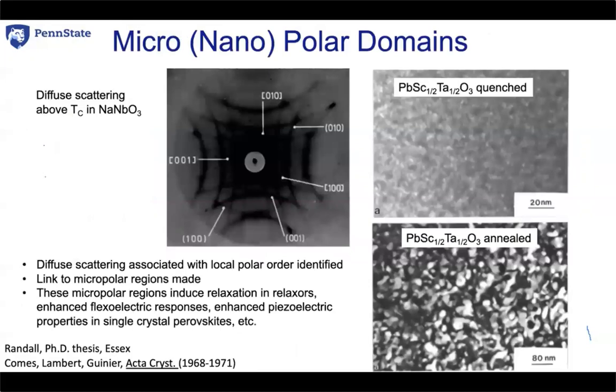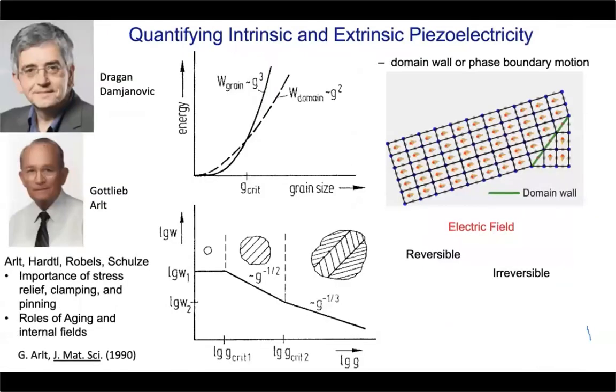Key early work on identifying nanopolar regions came from people like Clive Randall. This is from his PhD thesis at Essex University, where he was able to demonstrate in the TEM the observation of micropolar regions. This really was a confirmation of things that had been proposed by people like Comes, Lambert, and Guinier, that there would be residual polar clusters that are often observed above phase transition temperatures, even in normal ferroelectric materials.